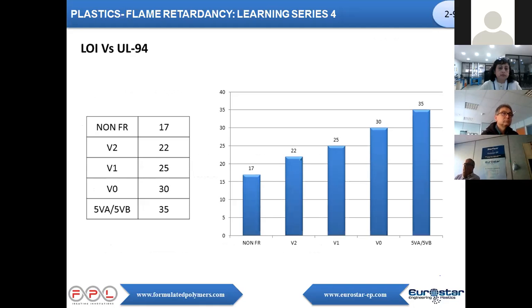In my last session of this FR series, we discussed in detail the UL flammability test. The slide shows the relationship between LOI versus UL94. Non-FR material meets LOI values below 20%. The slide graph shows LOI values increase with an increase of burning rating. V2 meets LOI of 22 and V1 falls in the range of 25. Rating V0 will be close to 30 LOI value. Then the highest ratings, 5VA and 5VB, match an LOI greater than 35. Flame retardant compounds have the highest values of LOI.